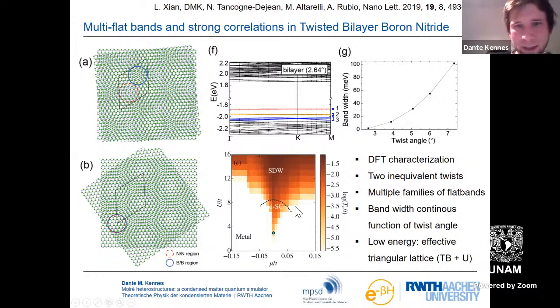And what we find in our study is that this axis can be tuned, as we proposed, by the twist angle. And you have a crossover from a metal into a d-wave superconducting state. And then at larger interaction, you would stabilize a spin density wave state.